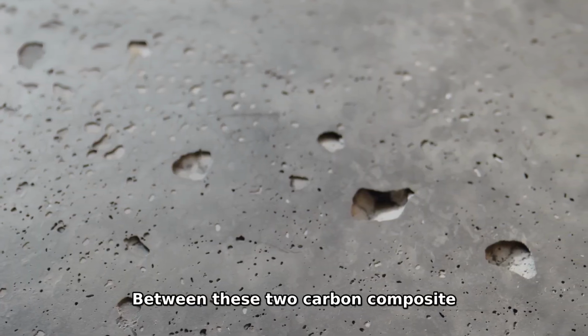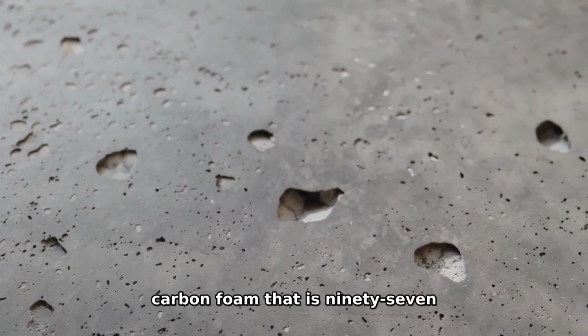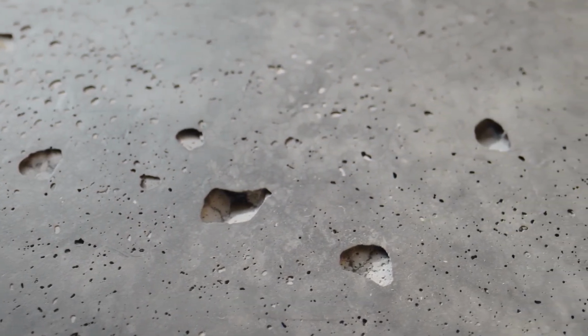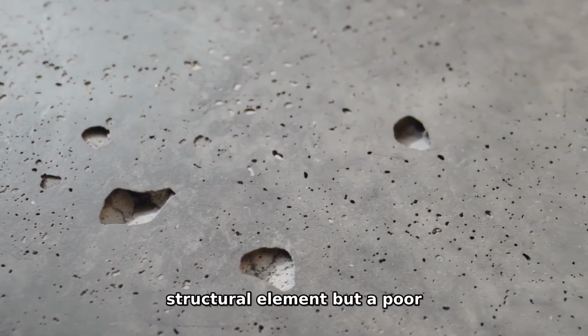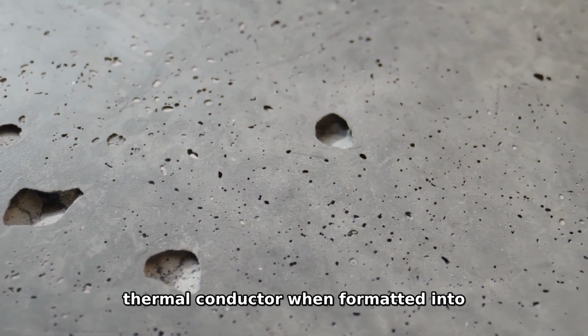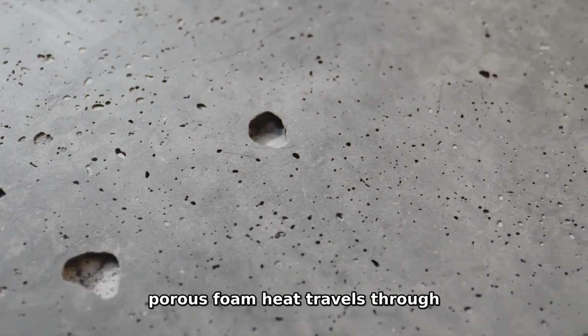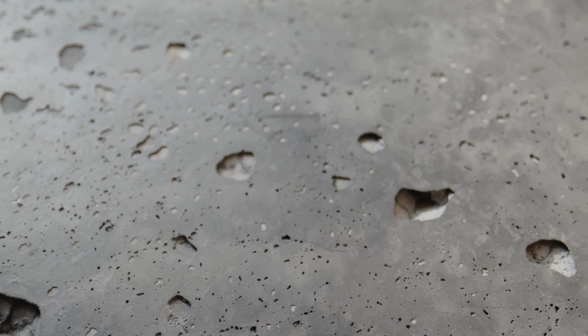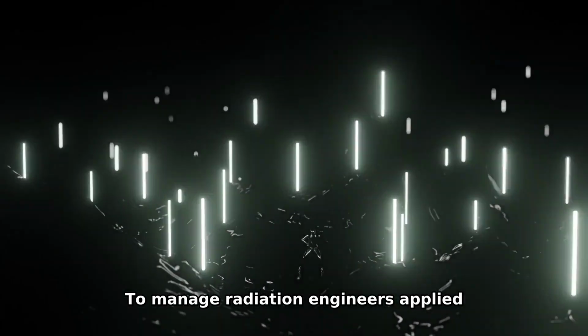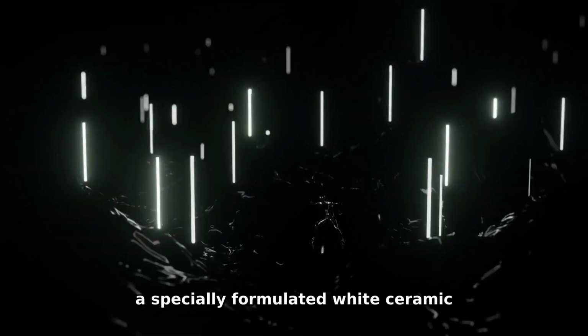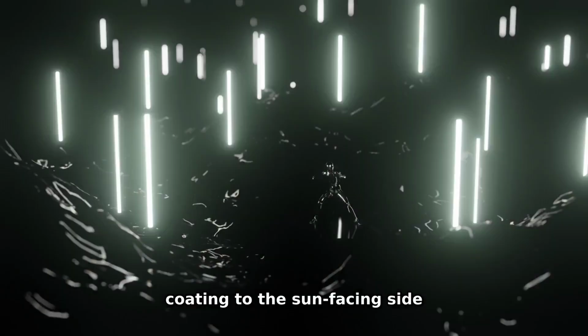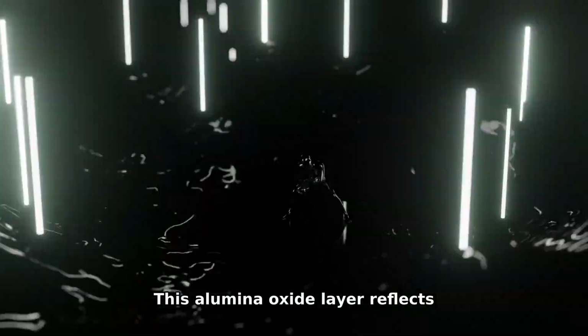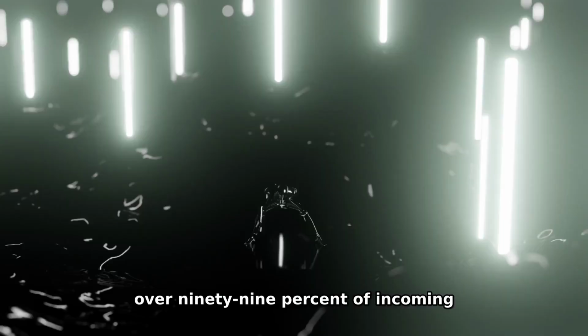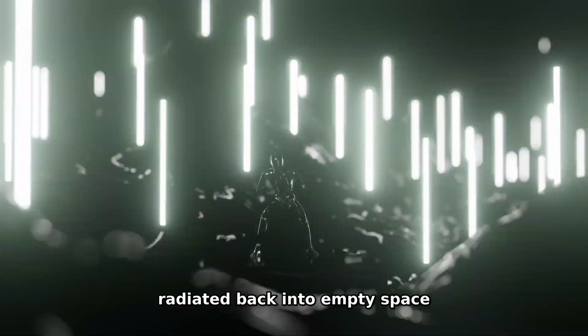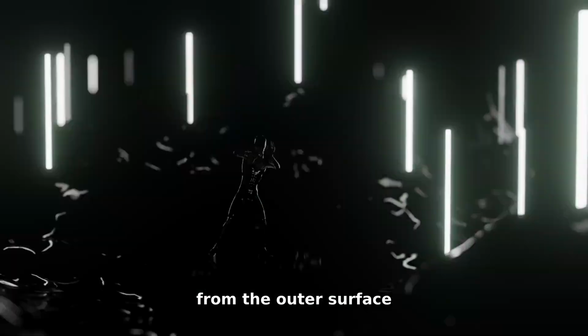Between these two carbon composite sheets lies a core of carbon foam that is 97% empty space. Because carbon is an excellent structural element but a poor thermal conductor when formatted into porous foam, heat travels through it extremely slowly. To manage radiation, engineers applied a specially formulated white ceramic coating to the sun-facing side. This alumina oxide layer reflects over 99% of incoming solar energy. The small fraction absorbed is radiated back into empty space from the outer surface.